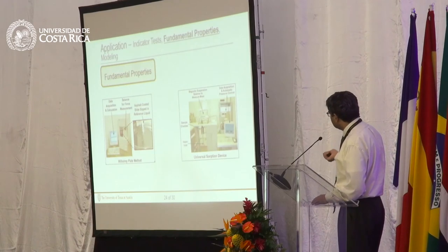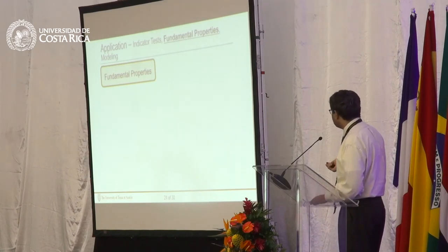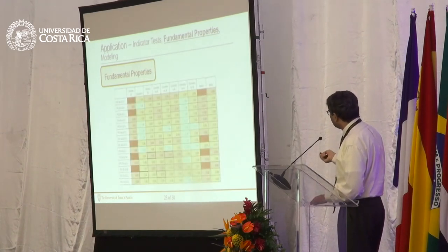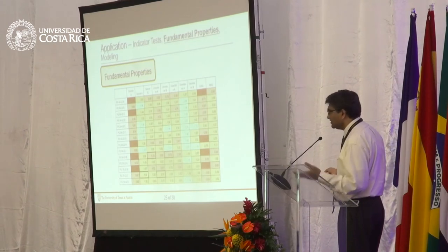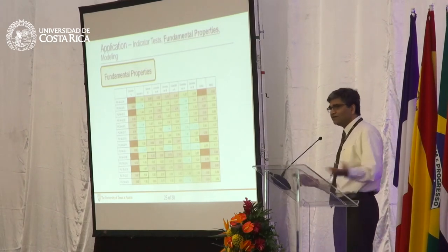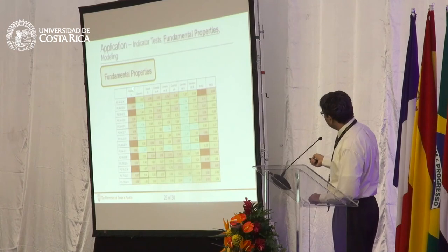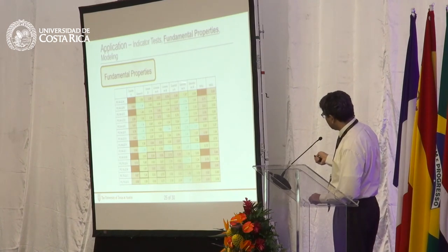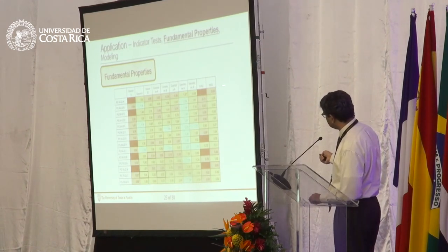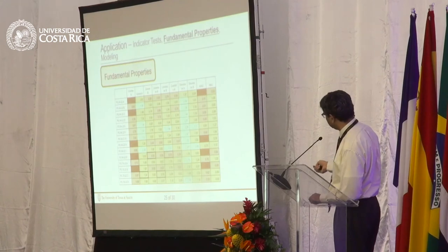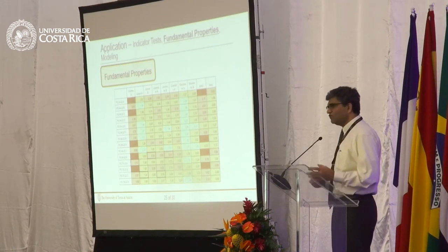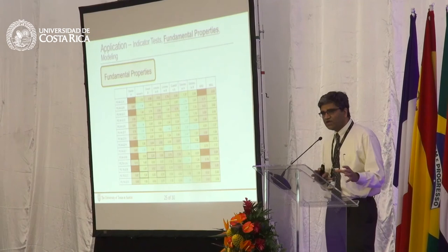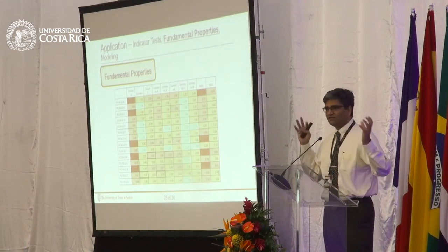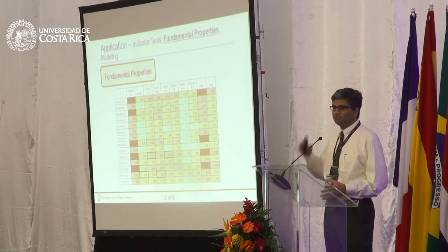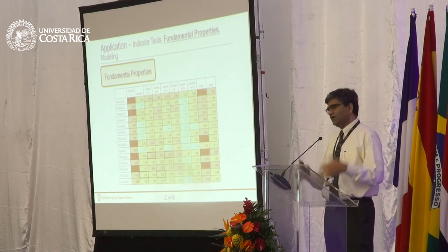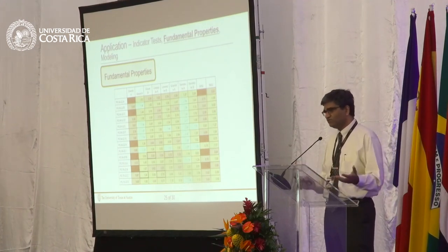So the first example I'm giving is surface energy, where you can do something like this. This is what we did for the Texas Department of Transportation. We created a catalog. Simply speaking, in several of the Texas districts, you had about 9 or 10 aggregates and 13 different binders. If you want to test how each aggregate works with each binder, that's 130, 140 different mixes, multiplied by replicates, multiplied by two tests, and you can have 5 years in the lab doing this.